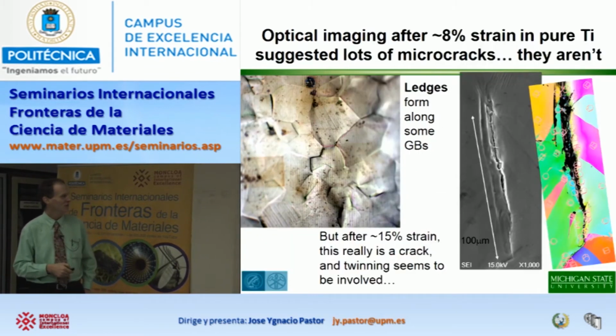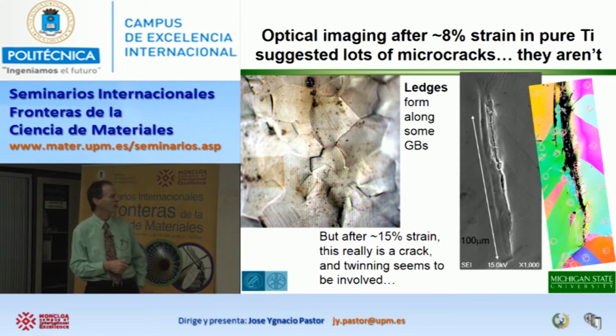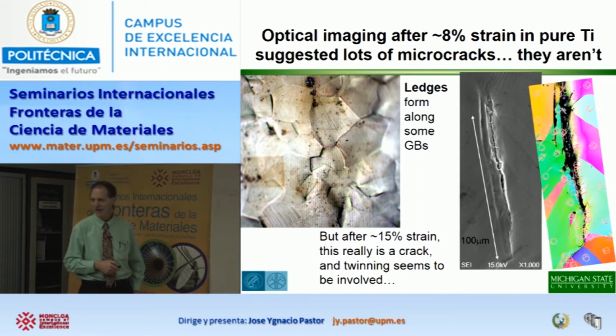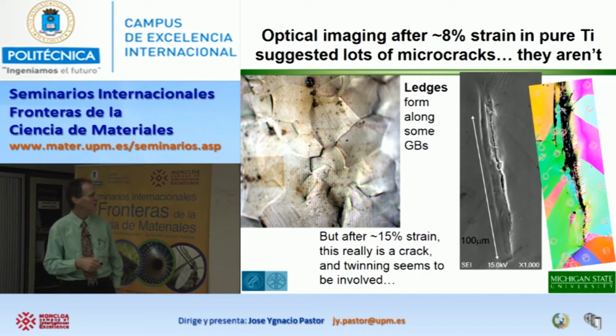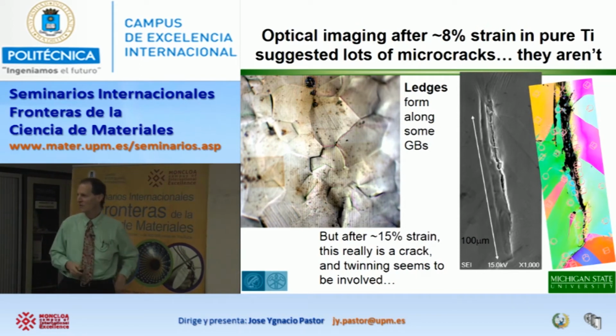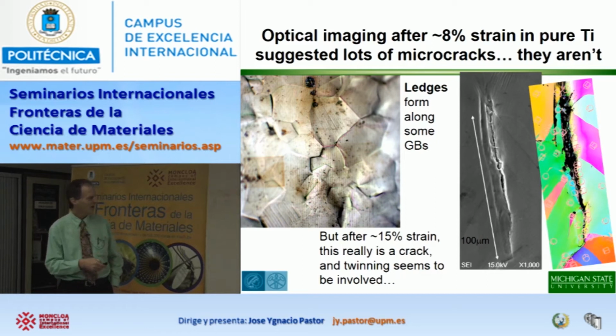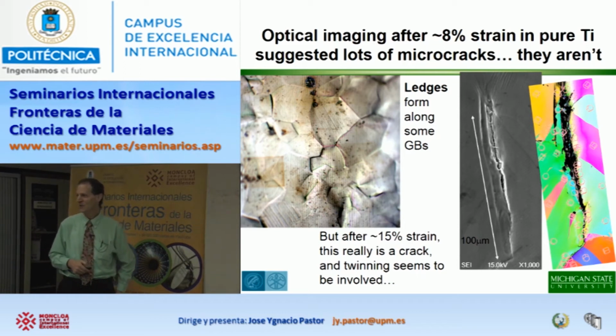So here's a polycrystal sample of pure titanium. And after we deformed it about 8%, it looks like there's cracks all over the place. If you just look at an optical micrograph, they're not really cracks. They're ledges. Some grains will sort of sink, and other grains will not. That leads to shadow effects that look like cracks, but they're not. But with a bit more strain, we really do see some real cracks. And if we look at the microstructure around them, there's lots of twins involved. So those twins here, too, seem to be involved with cracking at grain boundaries.